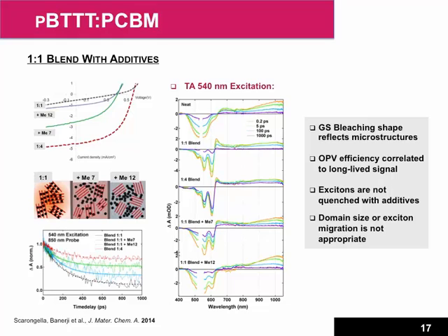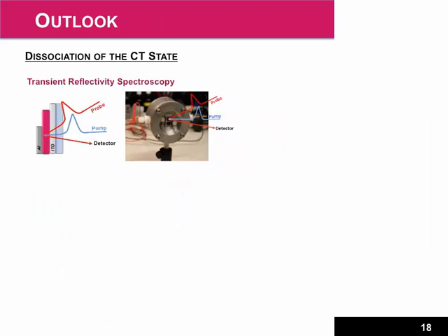And this is something that's very difficult to study using transient absorption spectroscopy, because here we always see the signature of charges, so we know whether the electron has been transferred to the fullerene, but we don't know whether the hole and the electron are still feeling each other, still close by, or whether they are completely dissociated into free charges. And that's why we had to change technique. We decided not to do those studies anymore on just the thin film of the material on a glass slide, which we did so far, but to actually work with entire solar cells.